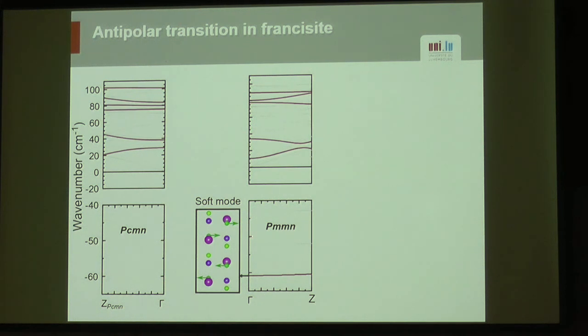Now, if we try to see how this mode translates, so to speak, to the low symmetry phase, you can make some projection and you realize that this chlorine motion is essentially here, okay? And this mode there, which is the one that you would assign to the modes seen in Raman spectroscopy, is not only about chlorine, but really a mixture of all those, so a bit of chlorine, oxygen, copper, et cetera, et cetera.